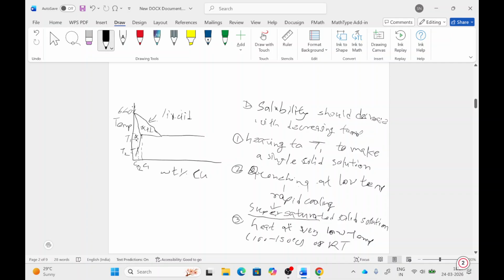When we keep it for a long time, with time the Al2Cu precipitates start to form in the aluminum matrix, meaning copper segregates slowly in the aluminum matrix and forms this intermetallic Al2Cu. So with a solid solution we can see this microstructure, which is completely alpha.